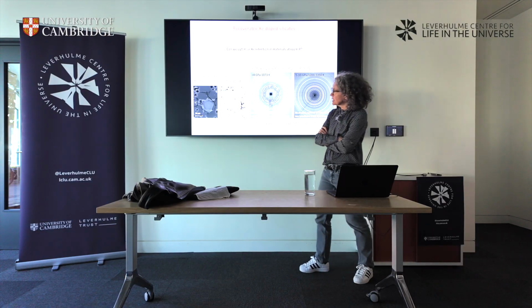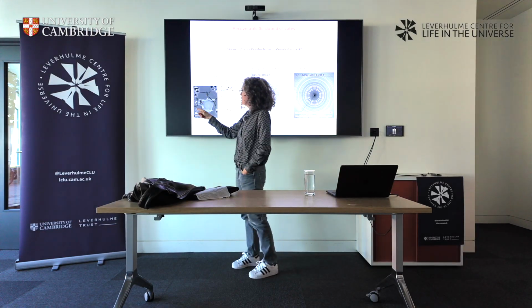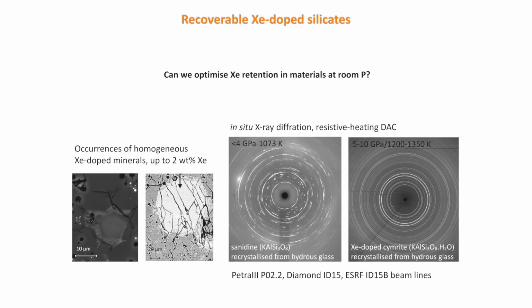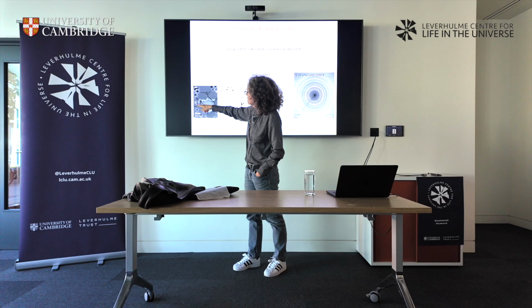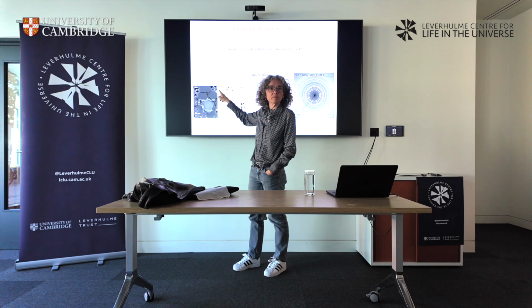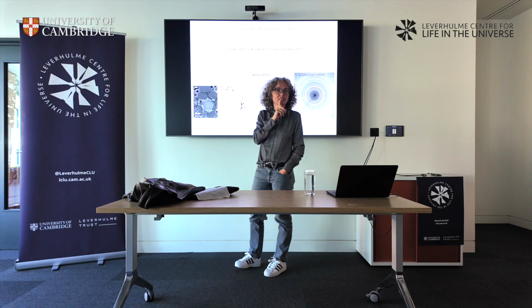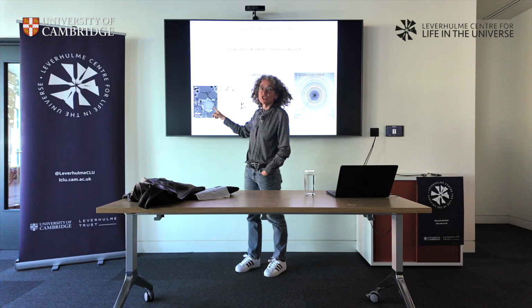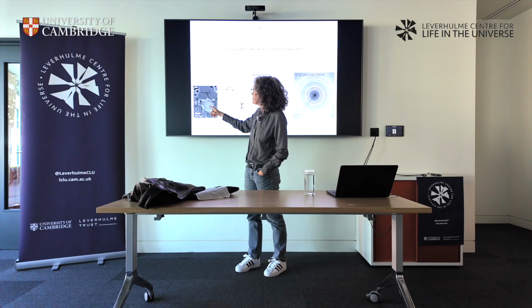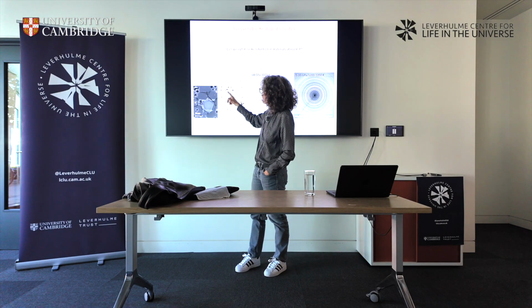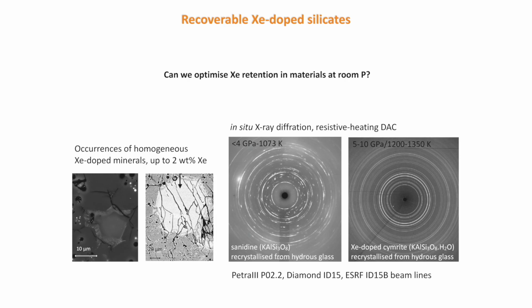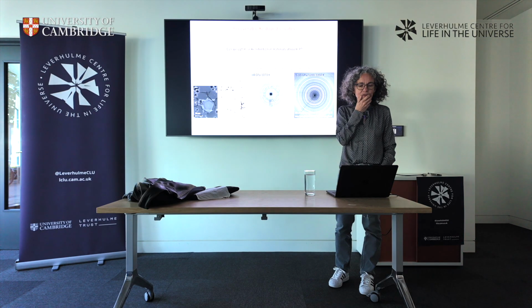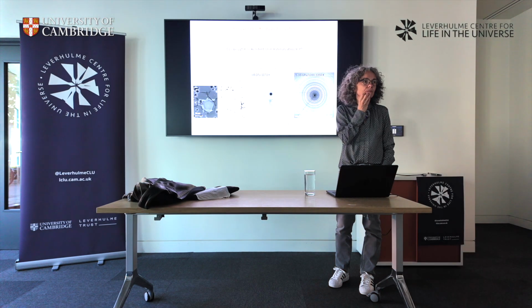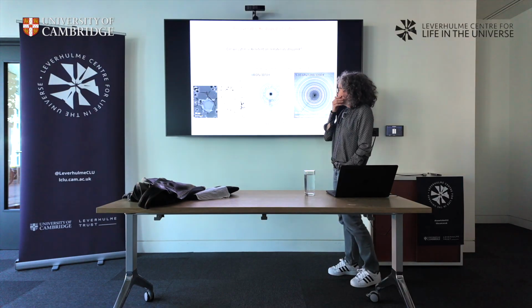So most of the time, as I said, this is an SEM image of feldspar doped with xenon. Most of the time we see these bubbles. I kept telling you about these bubbles, but not all the time. Sometimes the xenon is in homogeneous phases. We saw like this one, and in this one as well, we have a nice octahedra. Sometimes we have up to 2 weight percent xenon. So I say, well, from a materials point of view, that could be interesting to come up with xenon-doped materials that are stable at room conditions. So we tried to work on that.